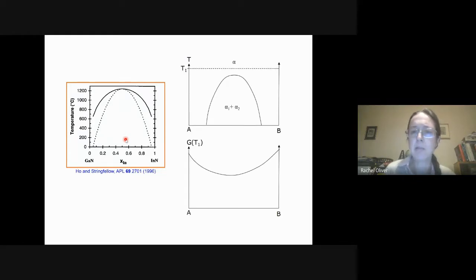Where does the phase diagram come from? Well, we look at the Gibbs free energy versus composition curve. So now I've got a material I'm calling an AB alloy. And at high temperature, which I'm calling T1 here, that Gibbs free energy versus composition curve has just a single minimum. And in that case, we expect random mixing of the A and B atoms.